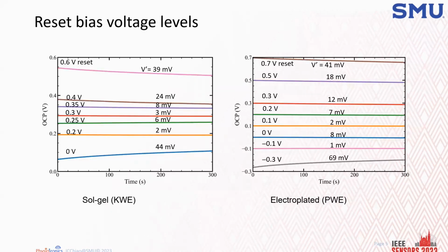So what we did first is that we put the sensor into a pH 7 PBS solution. PBS solution has enough salt that mimic the body fluidics. And then we test the sol-gel and the electroplated, and we put different potential, and we observe how the potential drift. We found out for sol-gel, if we apply 0.2 to 0.35 volts, the potential basically stays flat.